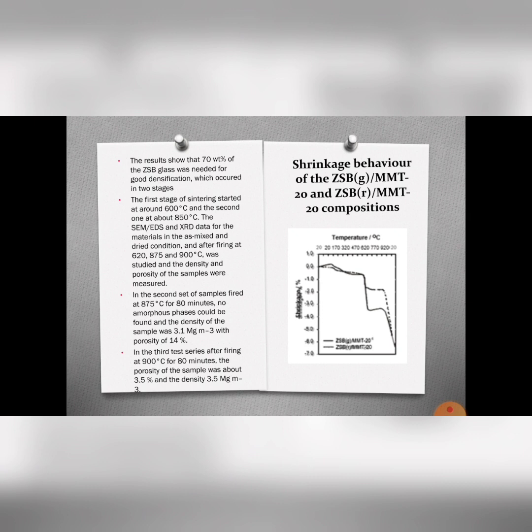In the third test series, after firing at 900 degrees Celsius for 80 minutes, the porosity of the sample was about 3.5% and the density is 3.5 Mg m^-3.